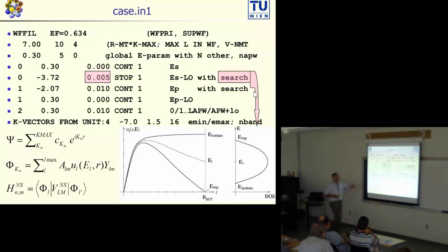And obviously, the radial wave function changes with energy in such a way, going from here all the way down up to here, schematically, right? I mean, this is only true for the hydrogen H2 dimer, the way I plotted here, but schematically it looks exactly like this. That means we are searching very quickly for energies where the radial wave function has either slope 0 or value 0, and that gives me the values of E bottom and E top, and with the arithmetic mean of these two values I get my mean band energy. This works surprisingly well and gives a very, very good and stable estimate of these semi-core energies and solves this problem. Okay?